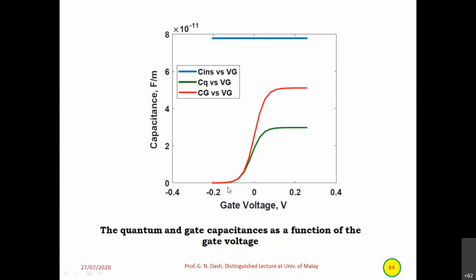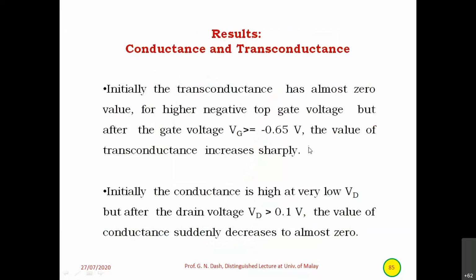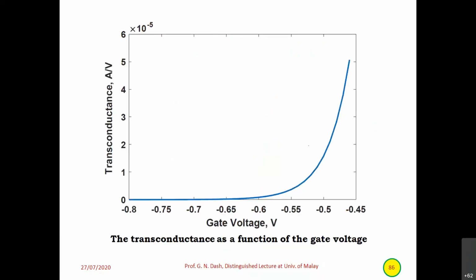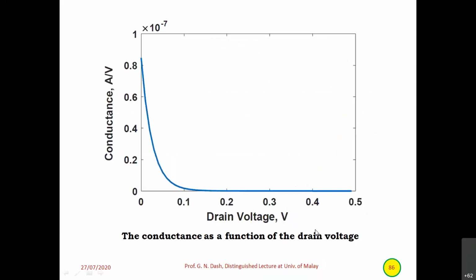From -0.2 to 0, it increases to almost half, and after 0 it rises suddenly, and at about 0.2 volt, it becomes saturated. Conductance and transconductance variations are like this. Up to 0.65 there is almost zero transconductance, and thereafter it rises steeply. Conductance is just the opposite: up to 0.1 volt it is very high, and after 0.1 volt, it reduces to almost 0.